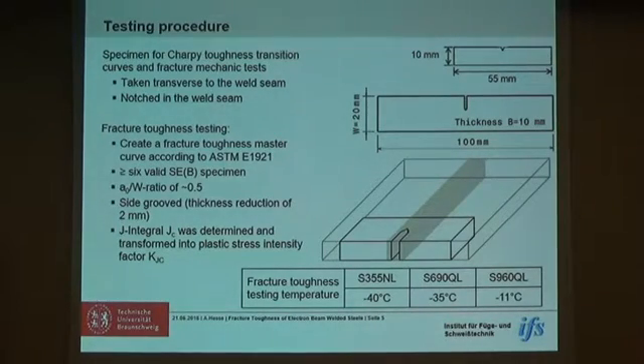For our tests, we took the specimens transverse to the weld seam. They were all notched in the middle of the weld seam, and the fracture toughness testing was done to create a fracture toughness master curve according to the American standard E1921, which needs at least 6 valid specimens. We chose a ratio of the initial pre-crack compared to the specimen height of roughly 0.5. The specimens were side grooved after pre-cracking, and the J integral was determined and transformed into the plane strain stress intensity factor KJC.